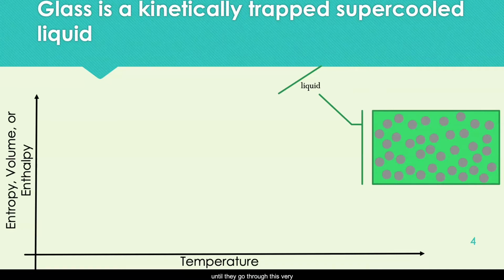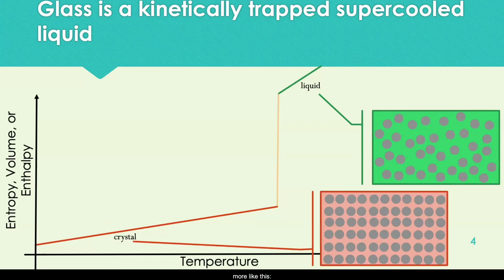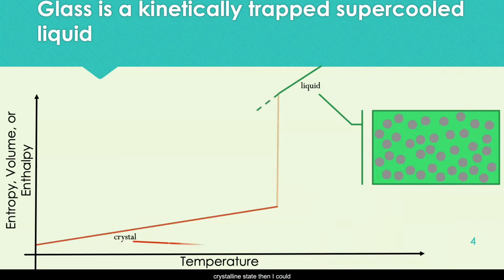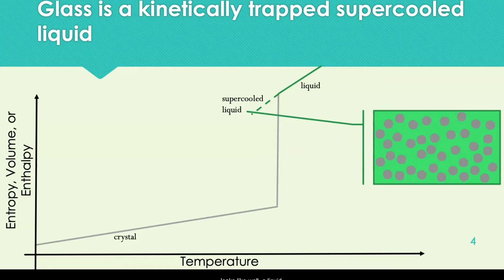they go through this very dramatic change, this phase transition, which occurs at the melting point and is to the crystalline state. As a crystal, the system looks more like this. It's very neatly packed, well organized in this crystalline structure. However, what if I could cool past the melting point and avoid the crystalline state? Then I could achieve a supercooled liquid, which continues to follow the liquid line and at a molecular level looks like, well, a liquid. It's still this random arrangement. It's just getting colder and it's getting slower.